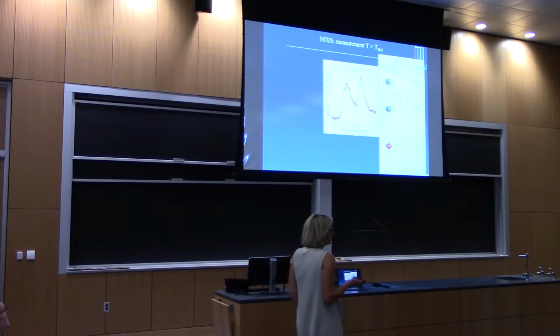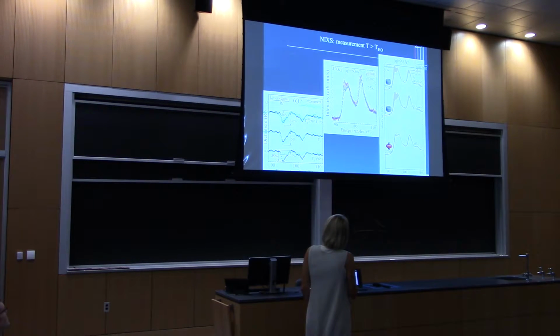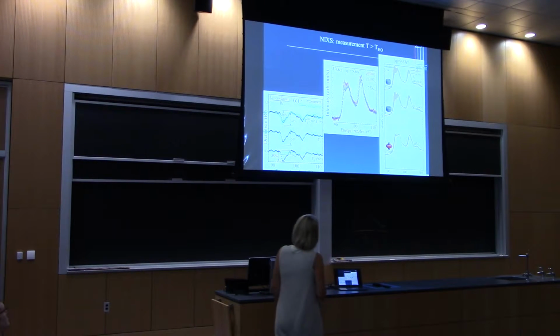So to be more quantitative, because this is a nice thing that you actually can do, quantitative simulation here. I compare the dichroism of these 3 states here with the measured dichroism. The black dots are the measured dichroism and the lines are the simulation. So I have a measured dichroism of 35%.